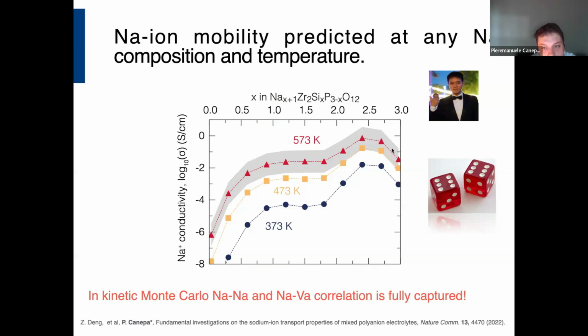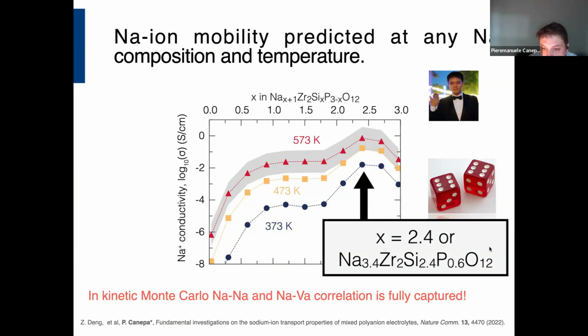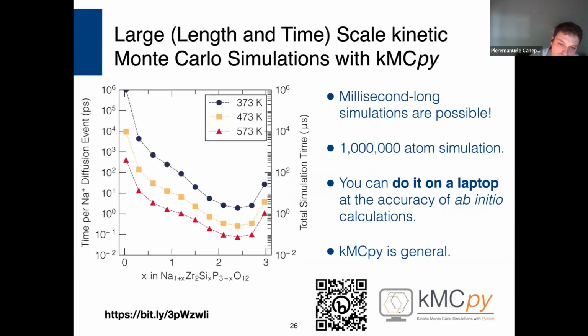And as you increase the silicon amount in the material, meaning that you limit the number of vacancies to the point that there are almost no vacancies, the transport decreases likewise. The beauty of using kinetic Monte Carlo in comparison to MD is that, one, you capture fully the correlation between sodium ion and sodium vacancy. And second of all, because of the nature of Monte Carlo, you describe the random distribution of the silicon, silicate, phosphate, sodium and vacancy fully in your model. This would be a very daunting task if you were to do molecular dynamics. But what comes out from this study is that you can identify that the highest conductivity is reached at sodium 3.4. And here again,